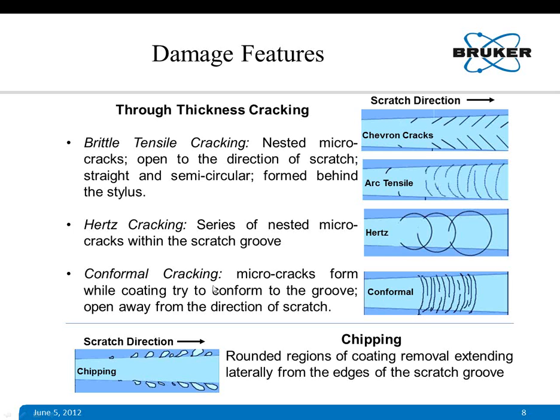Or there can be conformal cracking, micro cracks that are formed while the coating tries to conform to the groove. These are open away from the direction of scratch. Direction of scratch is this way, and the conformal cracks open in the other direction. Other types of damage features are chipping, which are related to adhesion failure.